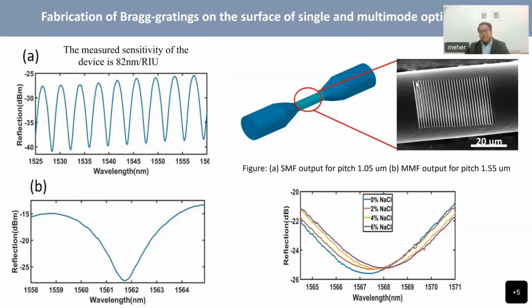So we etched the fiber to the core, and when we got the core, we etched the fiber core with the help of focused ion beam. What the focused ion beam does is we have gallium ions, and we put it in a very high vacuum, and we use these gallium ions to etch the material. This is etched up to the core, around 10 microns, and this is around 400 nanometers. So there is air, then silica, then air, silica, and this is the pattern generated by this grating.